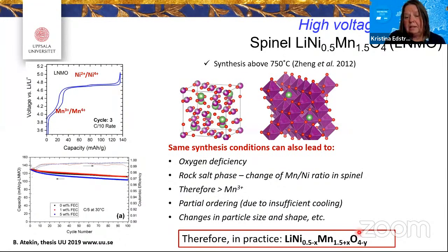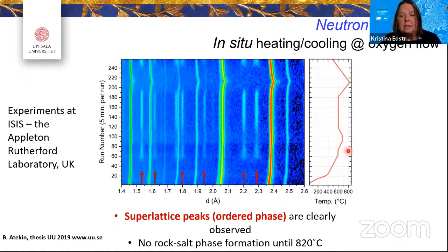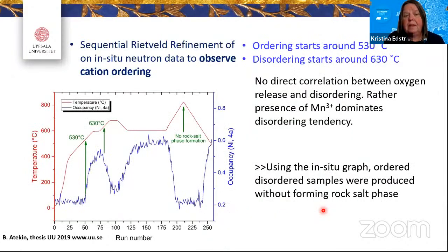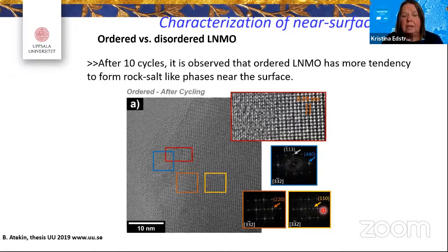And in practice, this material has a more complex structure. This is an example from ISIS where we have, under oxygen flow, tried to see where we can have the change from the ordered to the disordered phase and learn something about the stability of this sample, and see where the rock salt phase formation is happening. It turns out that the rock salt formation comes at rather high temperatures, which is of course an important sign for the synthesis people. But that is not enough, because you also have to look at what it looks like when you are putting it in your battery, when it's cycling.